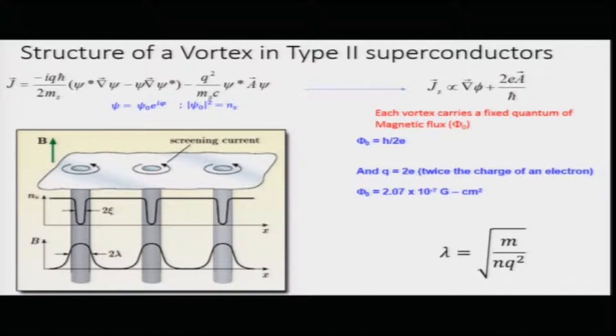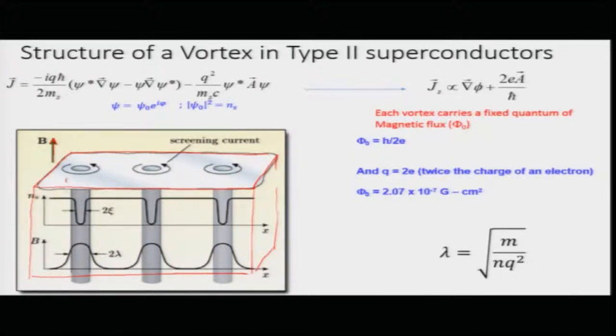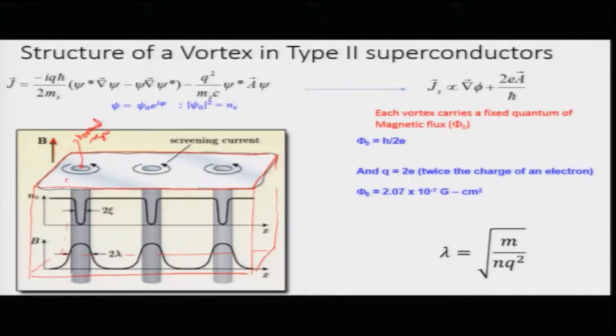One very important point about these vortices: if you apply a magnetic field to the superconductor, the vortices pass from end to end of the superconductor. They are like cylinders present inside the superconductor — these are normal cores, normal regions of the superconductor. If you apply a field where B is greater than Bc1 and less than Bc2, you will form these vortices in a Type 2 superconductor. The diameter of each vortex is twice the coherence length.